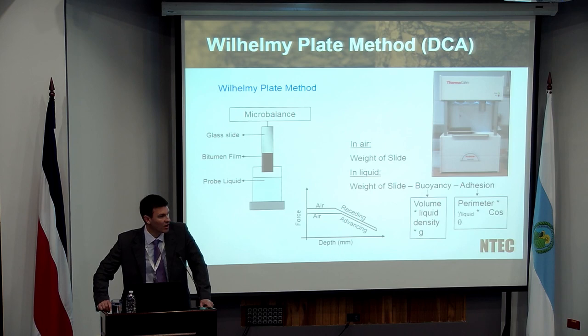We then can determine some knowns. Obviously, gravity is a known effect. We can actually take that into account. We can also take into account the effect of buoyancy. If we know the geometry of our glass slide and how much we are dropping it into the probe liquid, and if we know the density of that probe liquid, we can work out the effect of buoyancy. And finally, the only thing we don't know is the reaction between the glass slide with the bitumen coated on it and the probe liquid. That is the reaction between the two surface energy properties of those materials and the adhesion between the two of them. So that test is done using something called a Wilhelmy plate method.